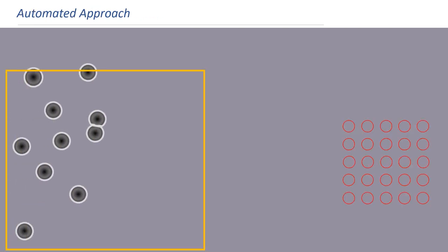I prepared an animation of what the particles look like from the perspective of the cameras at the build site to explain the systematic steps of the automated algorithm. The syringe pump keeps flowing the solution through the microchannel until the cameras detect spheres in the region marked by the orange box. Since the spheres are denser than their surrounding photocurable medium, they roll along the bottom of the underlit glass slide of the microchannel as the solution is pumped and they exhibit a distinctive white circular ring around their circumference when they are in focus as shown here. Image recognition algorithms assess defective spheres that are larger or smaller in diameter than is desired to make the crystal or that are permanently stuck together, and then optical tweezers shown as green circles are used to optically trap and displace the defective spheres to the region above the orange box where they are eventually disposed via the flow of the syringe pump.